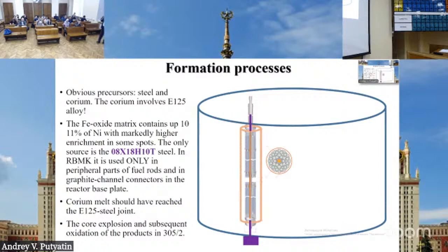Okay. I have one small question about these corium experiments in France. Did they use just uranium dioxide, or was it the full mixture of the elements, like 50 or 60 elements? No. This was basically uranium dioxide with some iron and zirconium. If you think about this, it is quite difficult to heat something like 200 kilograms simultaneously in a special oven from which you can pour it out. And this was done in an inductive oven.